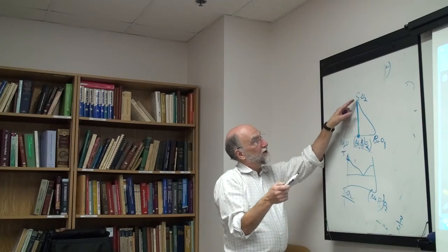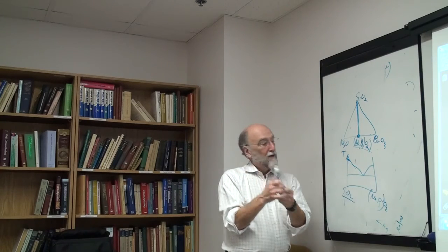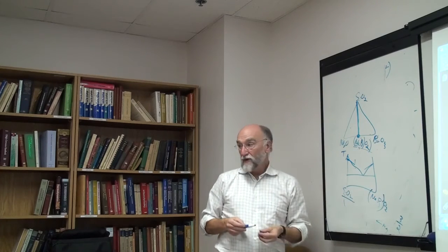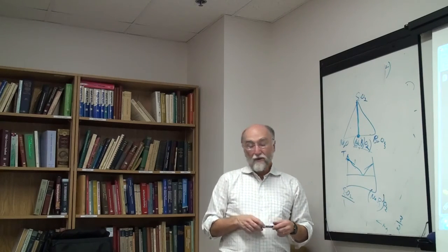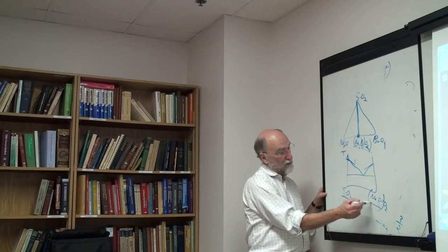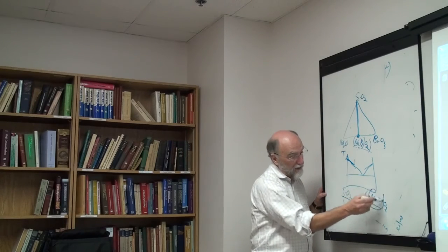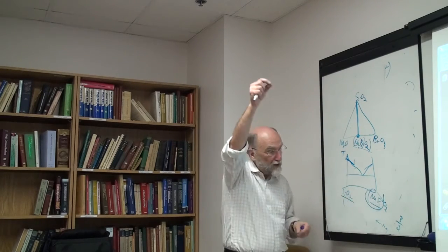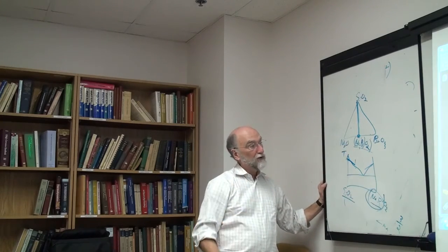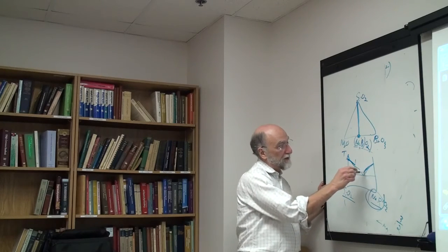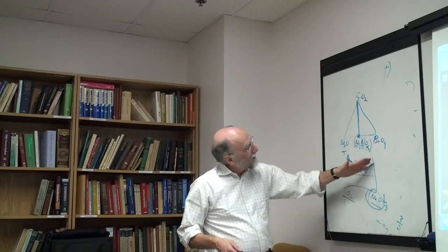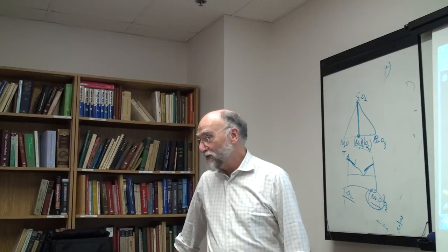Again, if the boron goes into the silica network with the sodium beside it, you really do get your limiting slope here and your limiting slope at the other end are very close to one particle slopes. Not perfectly in this case, but it indicates that to a first approximation, that's what's going on. Over this end, sodium and boron are replacing one silicon as a pair, which stays together. They do not go off independently, the sodium and boron stay together. So the boron occupies a silicon site with the sodium compensating the charge, and on the other side, it kind of indicates a similar thing, I'm not quite sure why. More complicated, but you're still getting pretty close to a one particle slope.